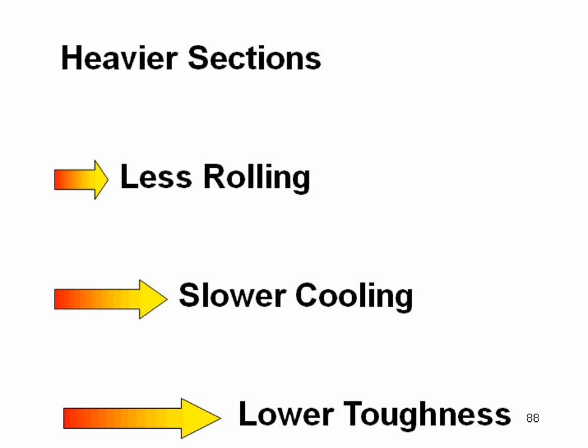There's less rolling associated with making the heavier shapes. They cool more slowly since we have thicker flanges and thicker webs, and that may lead to lower notch toughness. Now, notch toughness is typically measured with a Charpy impact test. That's not the only way we can measure that toughness, but it is a measure of the resistance to brittle fracture when we have a pre-existing crack in an applied or residual tension field. So these are the things that make welding on heavy shapes more of a challenge.